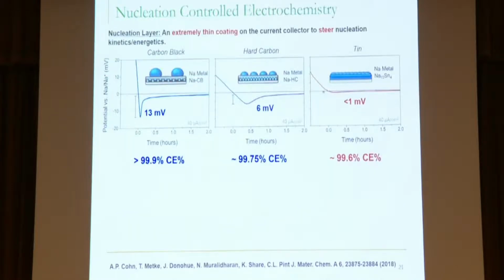And I won't go through all the details of that, but we tried a bunch of different types of materials. We're engineers, right? And there are materials like tin. Tin likes to alloy with sodium. So that means that tin and sodium like each other. What that means is that when it comes in, you don't see that big spike here that corresponds to nucleation. It just sort of grows, right?